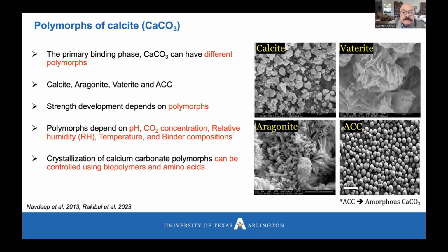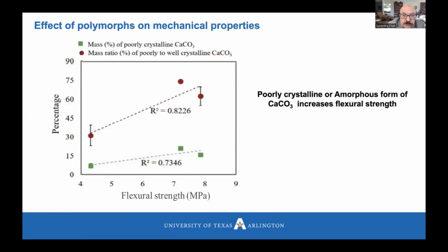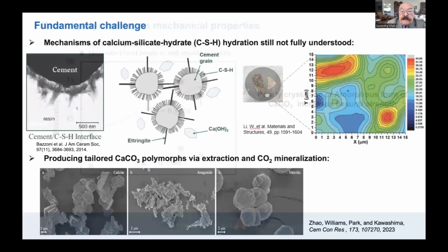For example, if you can increase the percentage of amorphous calcium carbonate, as shown here, then you can see you can increase the flexural strength. So poorly crystalline calcium carbonate, in fact, increases flexural strength. So, as I mentioned, controlling this morphology of calcium carbonate is very important.